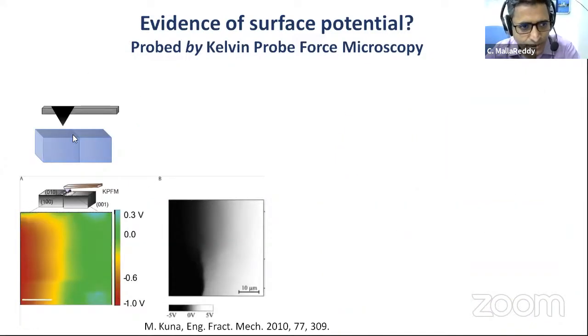We also looked at a crystal with a crack. This was not a very good self-healing crystal. Self-healing was not very efficient. We had a visible crack, but still the pieces were together. When we mapped across this crack line, we found negative charge on one side and positive charge on the other side. This also tells that there are opposite charges, and when it is not fully healed, there is a remnant charge. So when healing is not efficient, you have a penalty here. It has not reached its optimum stability, right? So you still have charges here.